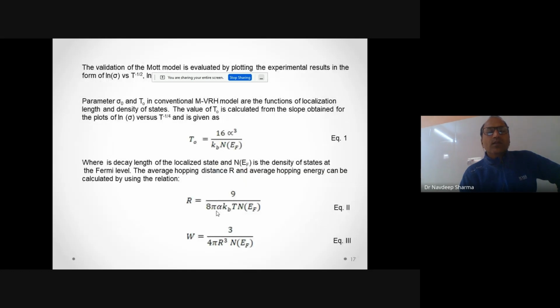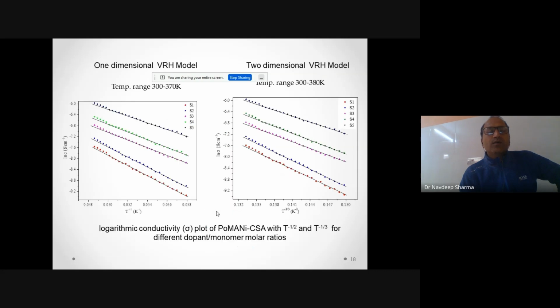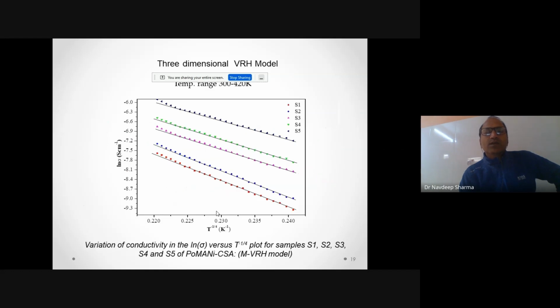And we have done this by using the different parameter T naught, and the average hopping distance and average hopping energy. We have explored that for one-dimensional, our conducting polymer is well applicable at 300 to 370 Kelvin, and below that the line is not fitting well. But in case of two-dimensional, the fitting is good up to 380 Kelvin, and after that it is not good. It means that it is applicable within this temperature range. And for the three-dimensional VRH model, the temperature range is 300 to 420 Kelvin, and at 420 Kelvin the model is fitting well and the charge transport behavior is showing better up to this, and not beyond this.